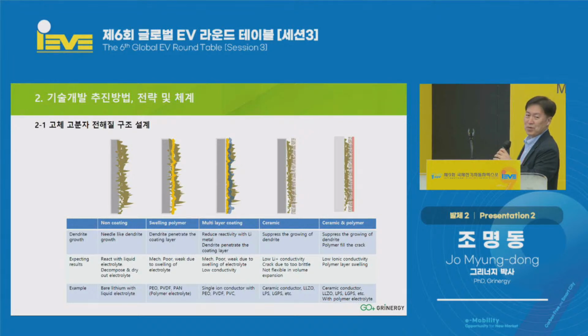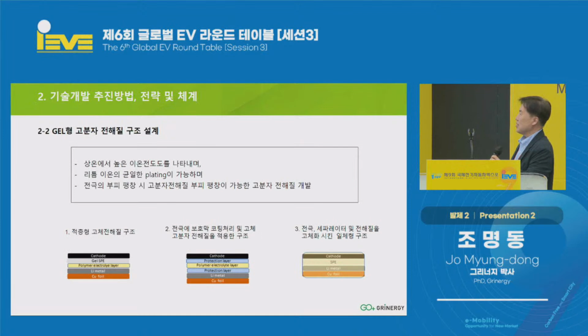And probably ceramic coating is likely to present the greatest possibility because ceramic can suppress the growing of the dendrite. So we partially achieved success, but once again, because of the volume expansion of the ceramic, there could be some cracks, and due to being brittle, it's not flexible. And now on top of the ceramic, there's a polymer coating to suppress the growing of the dendrite. And various efforts are made. So we have done everything, starting from non-coating, swelling polymer, multi-layer coating, ceramic, all the way to polymer. And we try to find the right answer.